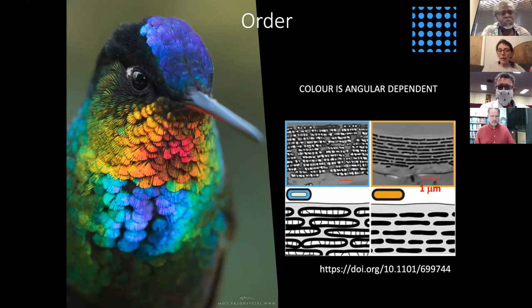But it's also important to say that the effect of color comes from the structure, but you also have the effect of absorption, right, that comes from the melanin pigment. But the melanin is like black. So what it means is that despite you using something absorbing, you are modulating the refractive index enough in such a way that you can still get reflection. So in nature, structural color is often, if not always, combined with pigmentation, but the color that you see is not because different feathers have different pigment, it's the photonic structures themselves. So the structure is exactly the same, you're just looking at it from a different angle.